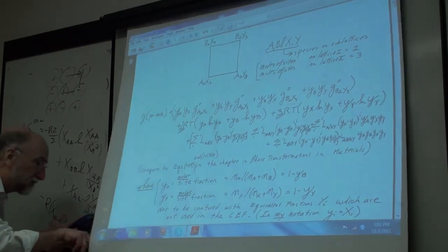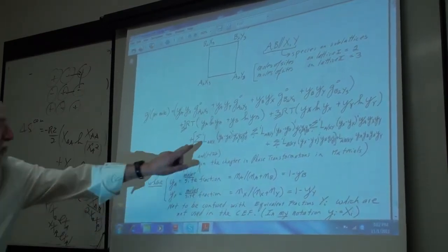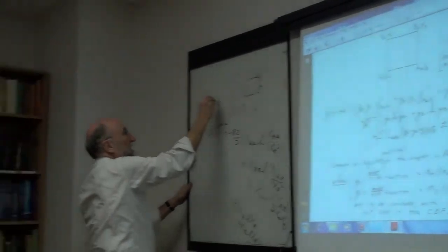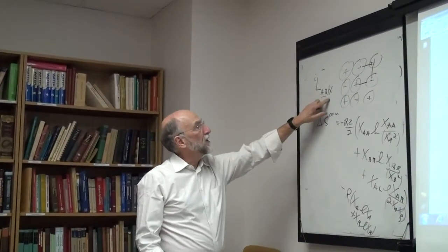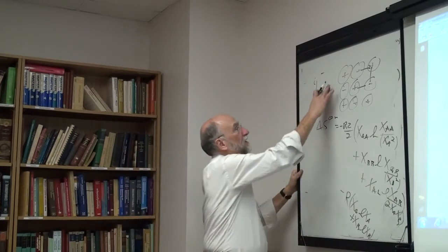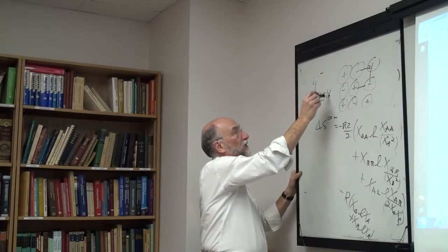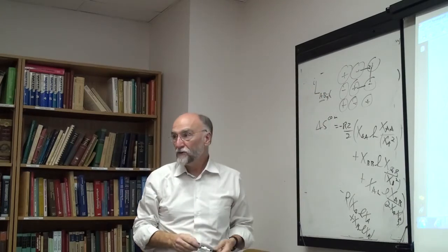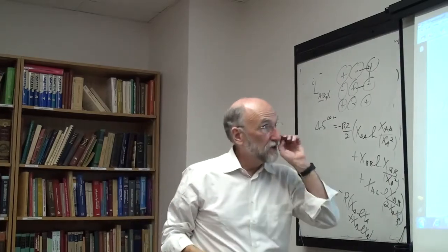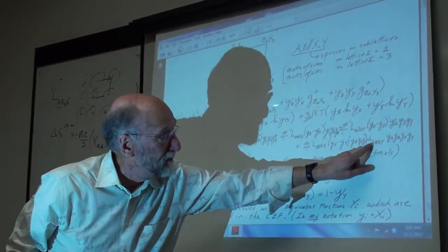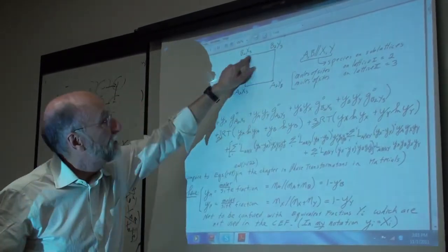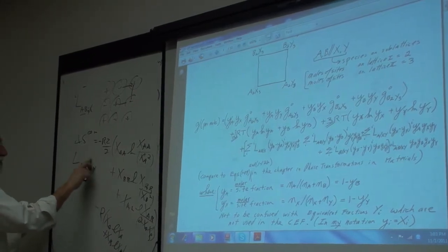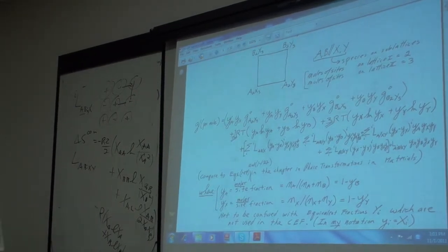Depends on whose paper you're reading, but these Redlich-Kister terms are written as iL, so this is AB slash X, your Redlich-Kister term for the AX, BX binary side. So it's the AB second nearest interactions when the other lattice is occupied by X, or sometimes there'll be a colon here, or a semicolon or something like that. This then is a reciprocal term, which is 0 in all 4 binary edges, and this will be written as L AB slash XY, or maybe AB colon XY or something like that.